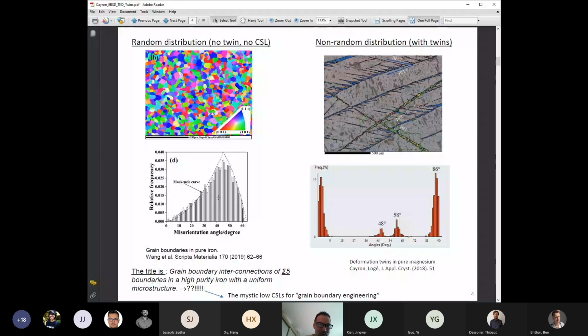So you have to compare your experimental distribution of misorientation with the Mackenzie curve. And here, for example, on the left side, it follows the Mackenzie curve very well. It means that the grains are randomly orientated. So it means that there are no twins, nothing special, and to me, there is no coincident site lattice, CSL. That's why it's surprising, because I took this image from a paper whose title was Grain Boundary Interconnection of Sigma 5. Sigma 5 is a kind of twin. It was surprising that they wanted to study Sigma 5 in this alloy that does not contain Sigma 5 if you look at the misorientation distribution. But anyway, let's go.